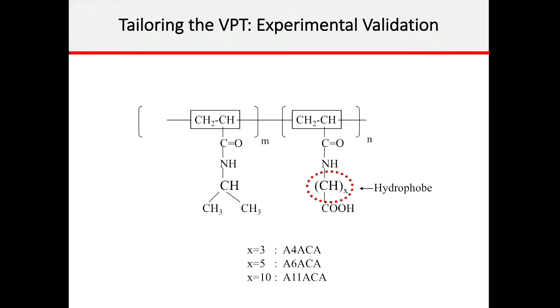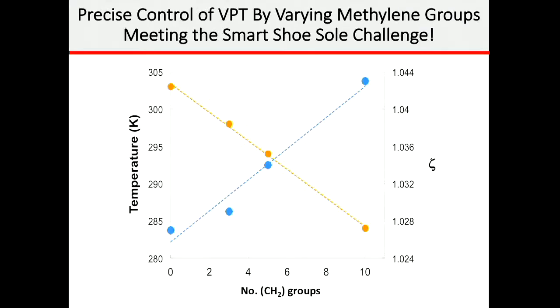We went into further experimental validation, and this is the most important part. We have the N-isopropyl acrylamide copolymerized with acryloyl amino acid here. And what is most important is this part. This is the methylene group. This is the hydrophobe. And the number of methylene groups you can change from 3 to 5 to 10. All right? So the hydrophobicity will keep on changing as you increase the number of alkyl groups, basically. So this is what we actually played with. And the experiment showed to us something very interesting. In fact, we saw that there can be a precise control of volume phase transition by varying the methylene groups. In fact, there was a 2 degree centigrade change with every addition of a methylene group, basically.